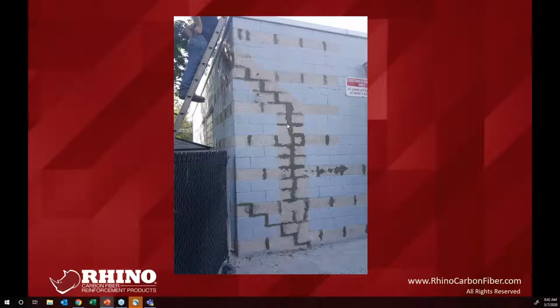They take it down to aggregate level to expose the pores, vacuum the walls. Do not use a blower. I tell people all the time when they do these installs, the single largest problem that we have is surface preparation. There's actually a study that was done at the University of Texas that shows that 99% of all failures in epoxy system application. It also counts for polys. It also counts for methyl acrylates and things like that. The single largest is surface preparation error.